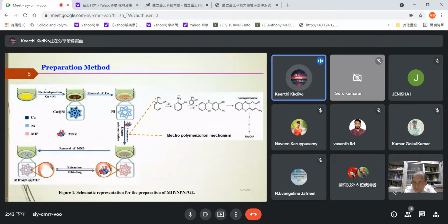Preparation method. Initially, copper and nickel were electrochemically deposited. Then the copper alone was removed from the electrode surface, which leaves cavities. Then electropolymerization was performed along with the drug metronidazole. Here, the authors have used orthophenylenediamine as the monomer. During the electropolymerization, an amine group is lost. The electron from the cation radical further reacts with another unit of the orthophenylenediamine and forms a dimer. This reaction continuously takes place and forms the polymer. After this, the drug alone is extracted from the electrode surface, which leaves the imprinted sites over the electrode surface. It was used as the working electrode.